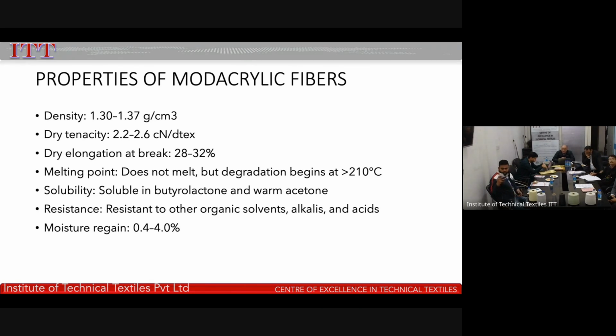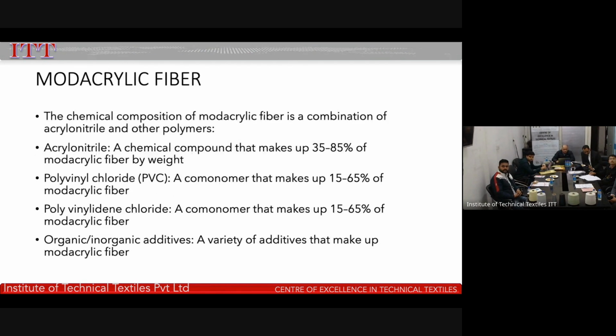It does not melt, but it degrades at 200 degrees centigrade, basically soluble in warm acetone. It is generally resistant to organic solvents, alkalis, and acids, moisture regain of around 4%. Now, acrylic is 100% polyacrylonitrile. If a percentage of polyvinyl chloride or polyvinylidene chloride is mixed to it, that is what forms modacrylic.